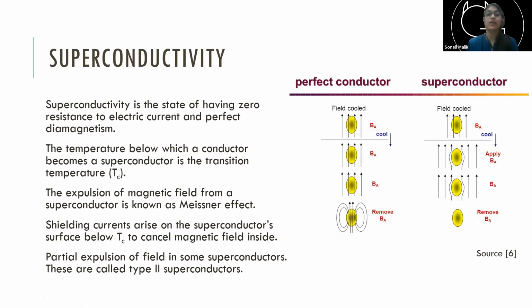So one interesting thing is how does a superconductor cancel any magnetic field inside it once it becomes superconducting. So there are shielding currents that arise only in a particular thickness, which is called the penetration depth of a superconductor, which cancel all the magnetic fields inside. And superconductors are classified in two types, type 1 superconductor and type 2 superconductor. So type 2 superconductors have the property of partial expulsion of a magnetic field. So above a certain critical magnetic field, they will allow, say, a small amount of the magnetic field to go through them, but they still maintain superconductivity in most of their bulk.